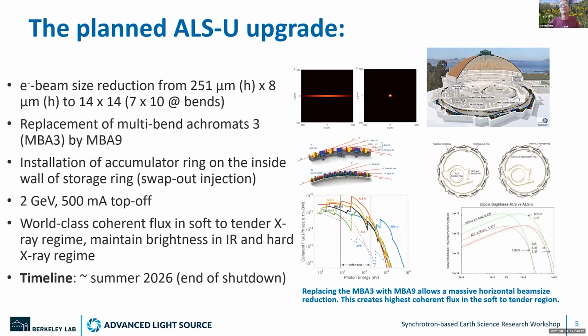An additional feature of the ALS, which I don't think the APS nor the ESRF have, is that in order to guarantee continuous smooth top-off operation, we actually install a completely separate storage ring on the inside of the current storage ring. This is shown on this graph. This additional storage ring, named the accumulator ring, will be used to dampen the oscillations in the electron bunches, and thus enable what they call swap-out injection on the run at 500 milliamps. The new storage ring will operate at 2 giga-electron volts. That means we're actually going a little up, not down as the APS, and we continue at 500 milliamps.